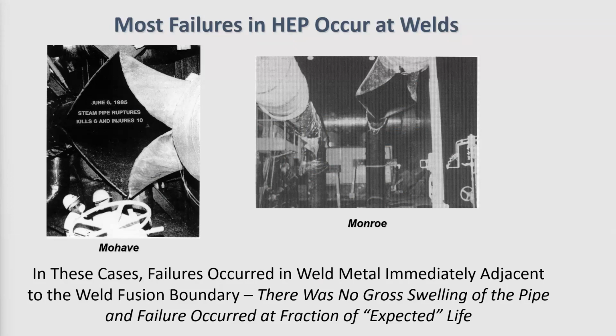A very well-known example here in the United States anyway, and this is going back to the mid-1980s, there were two highly publicized failures that occurred in long seam welded components. These were in traditional coal-fired power plants on hot reheat line piping. In both cases, these failures occurred at the weld seams. There was no gross swelling of the piping involved. In fact, there was virtually no indication of any distress in the piping prior to the failures occurring. And in both cases, these failures occurred at a fraction of what would have been the expected life based on consideration of the properties of the base metal.